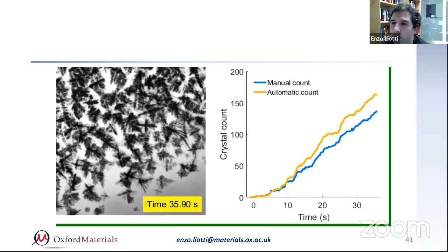That means that the lead will basically form liquid droplets within the liquid aluminum. And we have used that to start to measure the flow in the interdendritic region, right? So you can get information about the fluid flow in the mushy zone at high solid fraction. What would be difficult to do is replicate the flow of a filling system. So if you've got a normal casting, sand casting, that is probably still better done with other methods. Also because the scale of our imaging is quite small, so it would be a very local measurement.